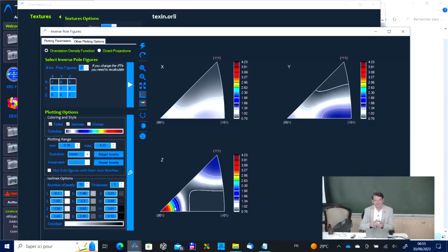So it must have been a bar from the symmetry, from the distribution. Anyway, we had the sample and we were doing tensile testing on it. But from the texture, without seeing the sample, I can tell you this was a bar. That's for sure. It was a round bar.